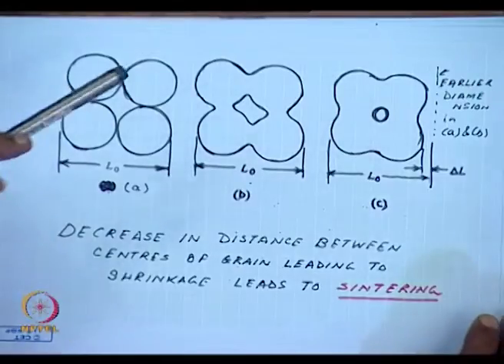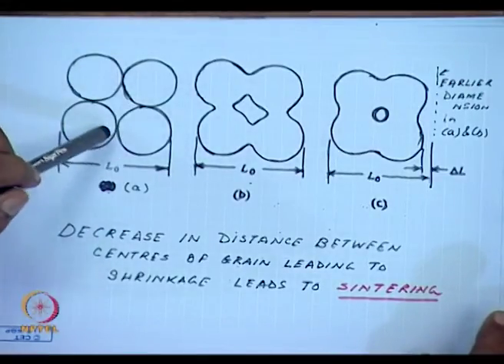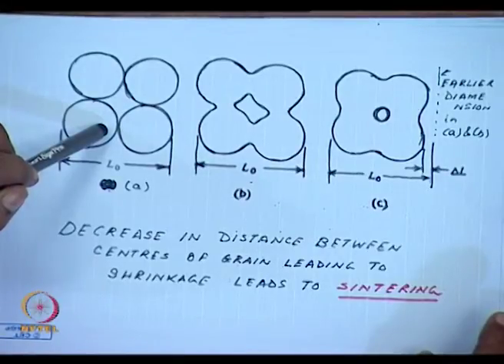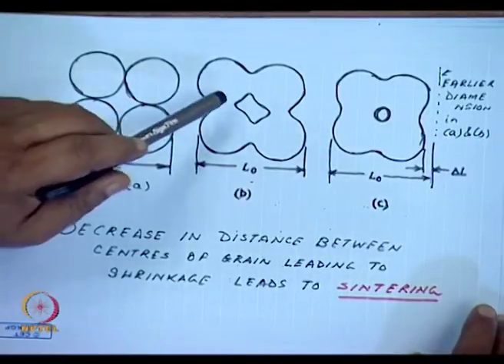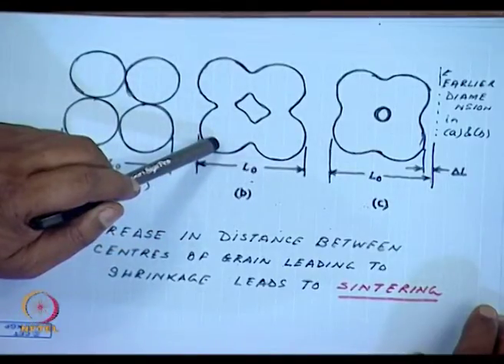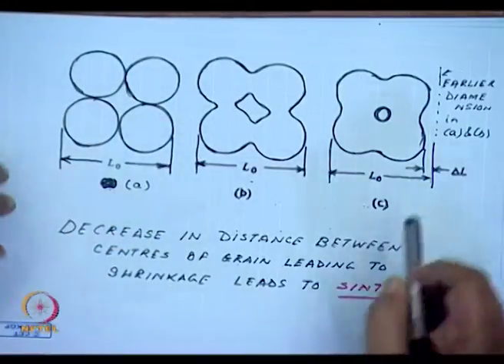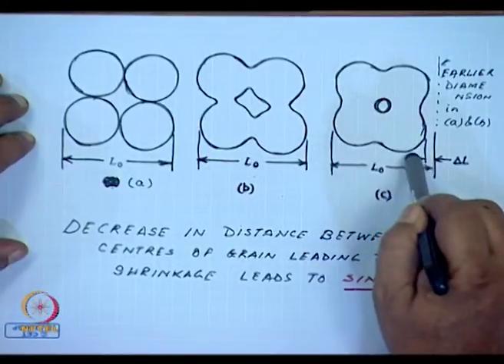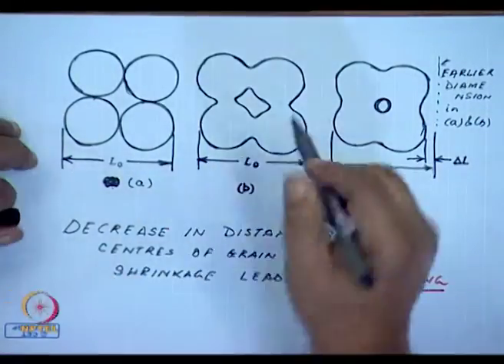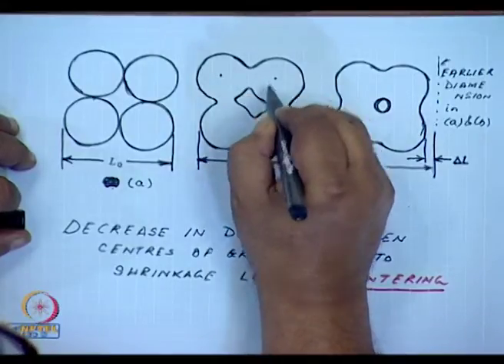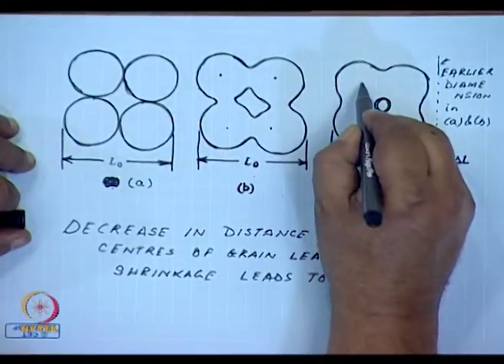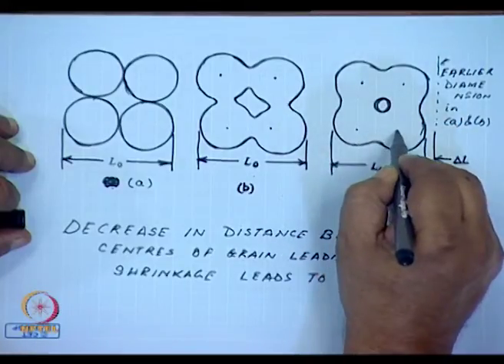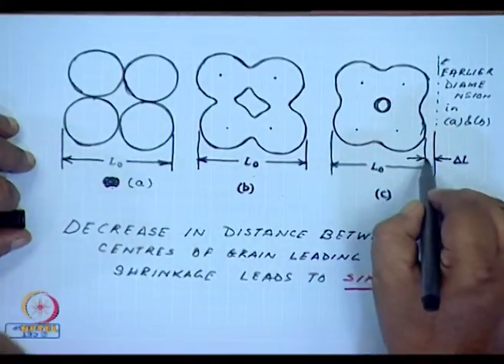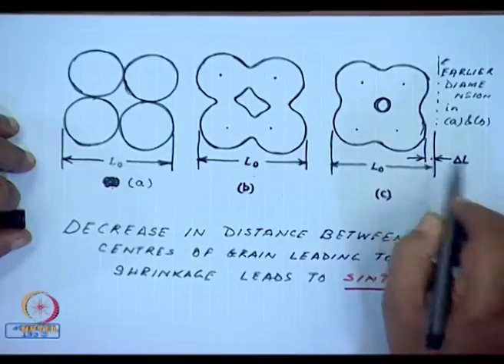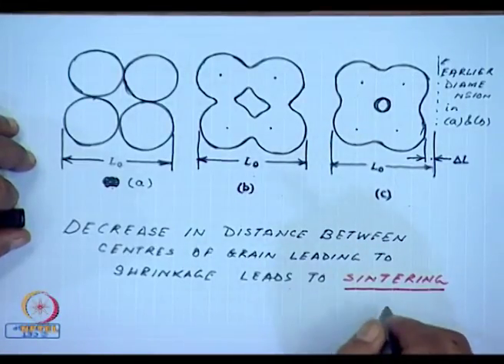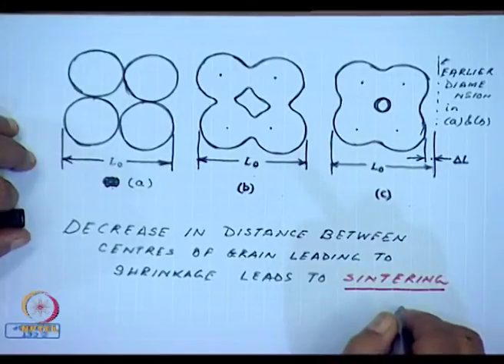Here I have drawn 4 idealized spherical particles. During sintering, what happens? Mass transfer takes place. Sintering only happens if the distance between the two centers decrease, which has happened over here. There has been a shrinkage. Only in this case do we call it real sintering has happened.